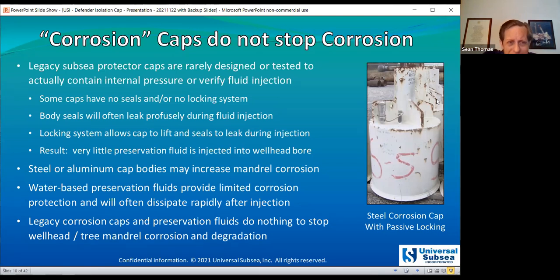The ones that do have body seals typically leak profusely during the fluid injection process. The locking systems tend to be fairly low-cost, and due to the pressure during injection, which generates a pressure force inside the cap, the cap will lift up against the locking system. That's the phenomenon by which most of these caps end up with leaking seals. The consequence is that very little preservation fluid is actually injected down into the wellhead bore.